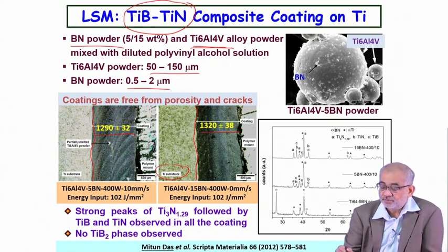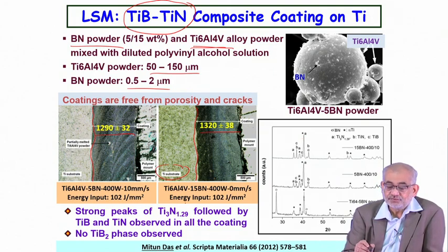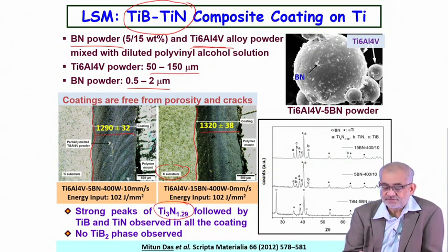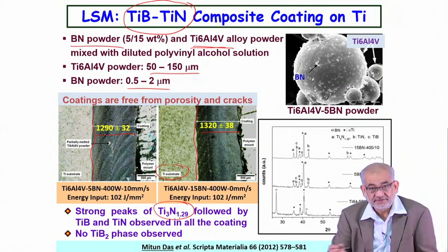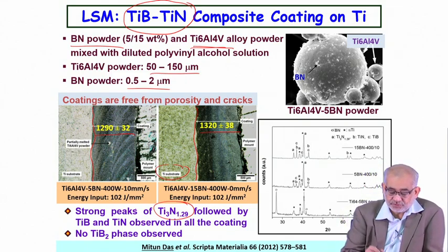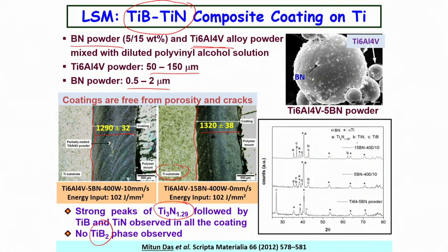What is also important for us to note is that we intend to produce boride and nitride, but the nitride that we develop actually is not a stoichiometric nitride, and that's possible because there are defects in the crystal itself. So crystalline defects make these kinds of coatings slightly deviate from the usual stoichiometry. In this approach, TiB2 was never formed, but we did form various other forms of borides. So the precursor is the powder mixture, and what we develop will be various kinds of complex nitrides and borides, but not necessarily diborides.